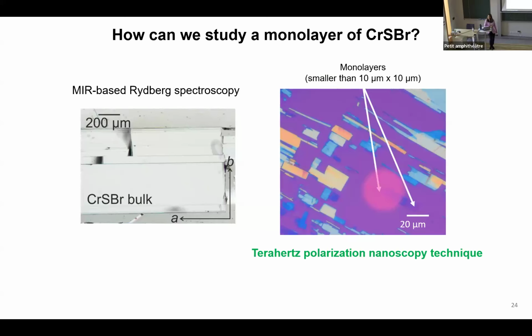Just a completely ignorant question. How does this compare to other 2D materials in terms of the size of the monolayer region that you're able to get? Yeah, in some transition metal dichalcogenides, you can get millimeter size monolayers, for instance. But in chromium sulfide bromide or 2D magnets, for the moment, the exfoliated sizes that have been achieved by mechanical exfoliation are that tiny. And yet I have to say that CrSBr is not that bad.